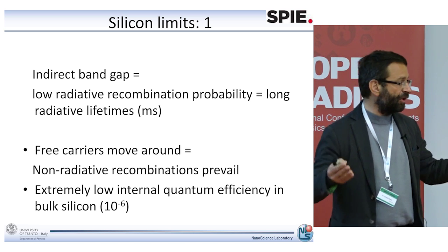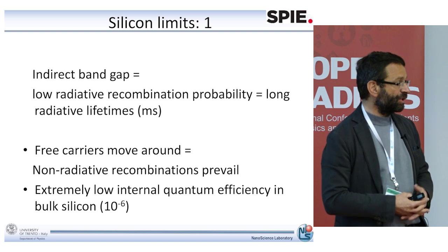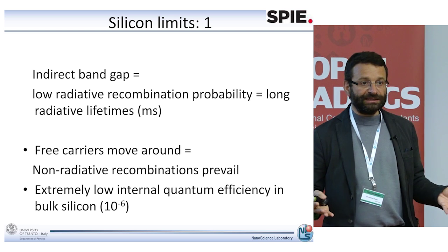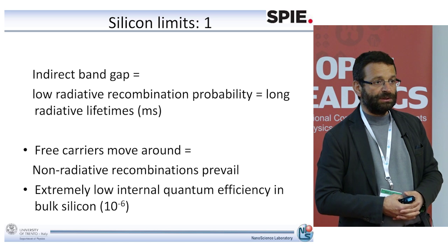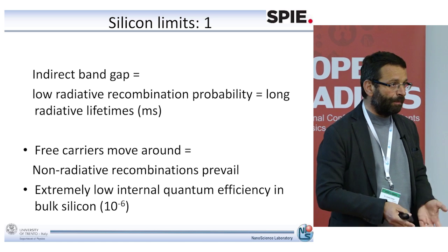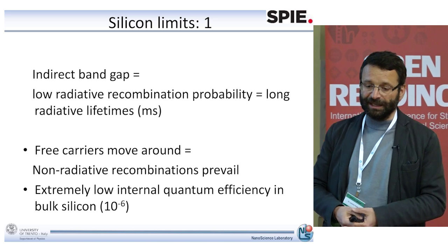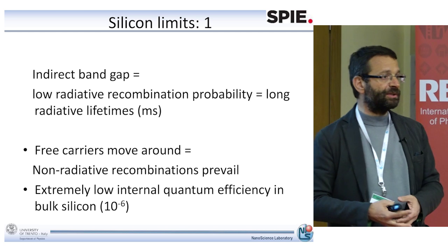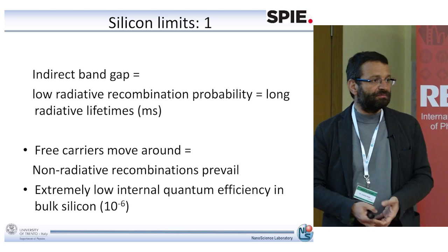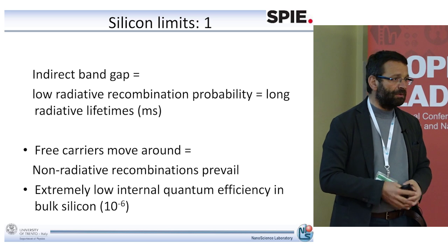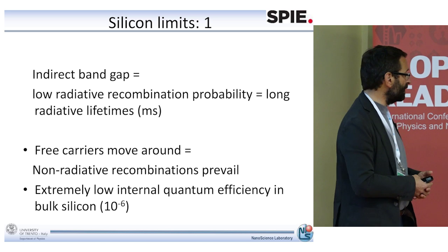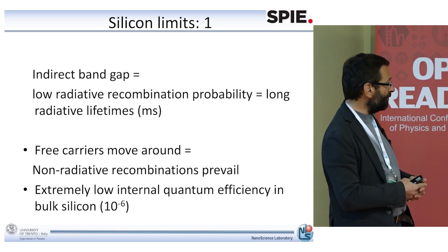For example, the erbium-doped fibers. So we do buy erbium lasers in fibers. The lifetime of the metastable state in erbium fibers is 13 milliseconds, which is more or less the same as in silicon. What is the problem with silicon?